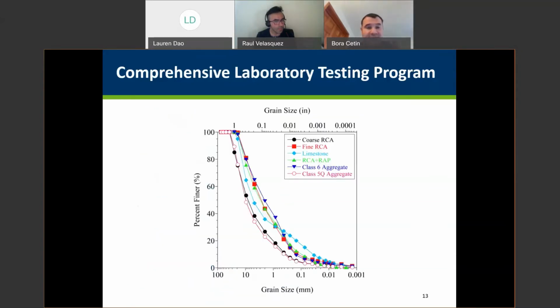Here is the particle size distribution of the materials that we will discuss today. As you can see, the bottom two lines, the coarse RCA and Class 5Q aggregate, seem in the beginning to have a coarser gradation compared to the other four materials, but again, after compaction, their gradation also shifted to the right to become finer, close to the gradation characteristics of the other four materials. Next slide, please.